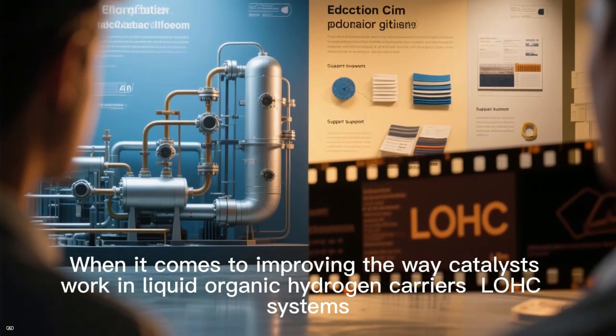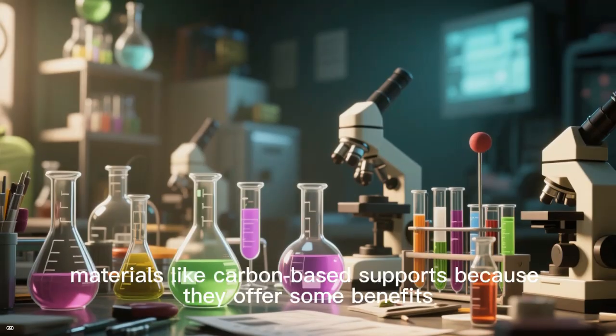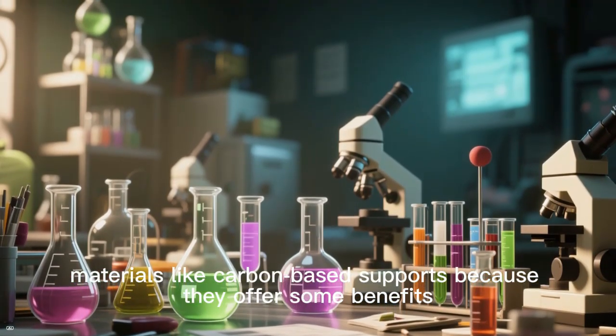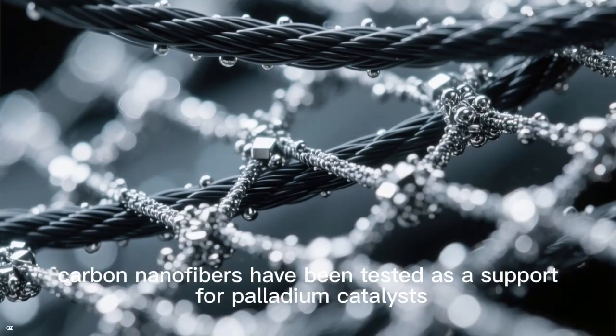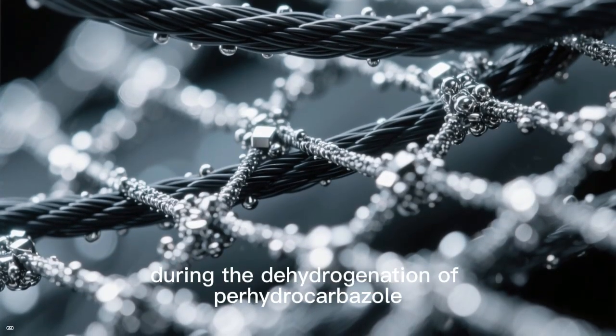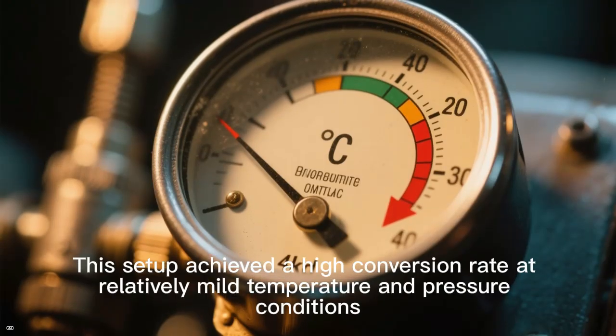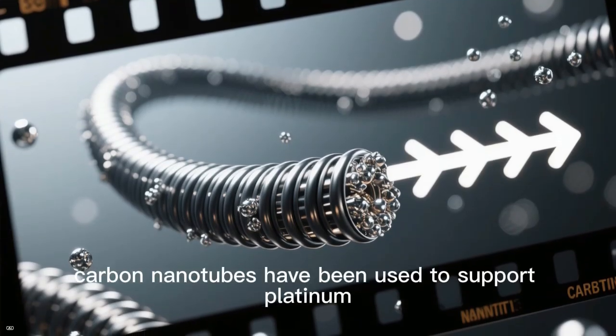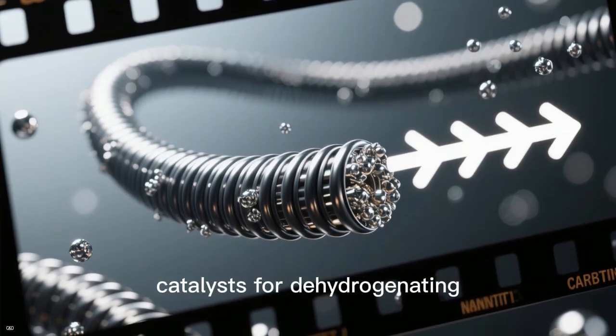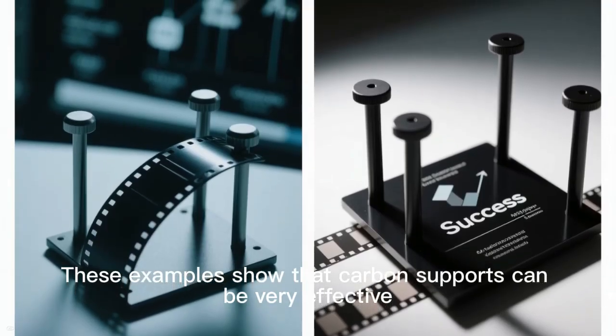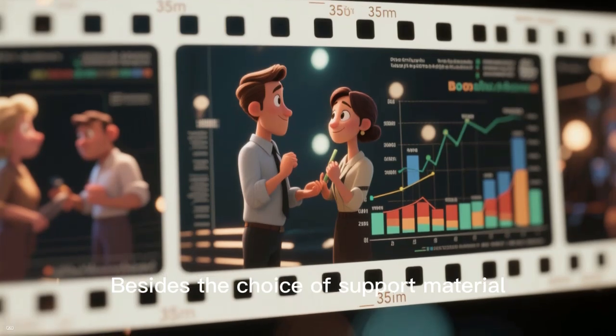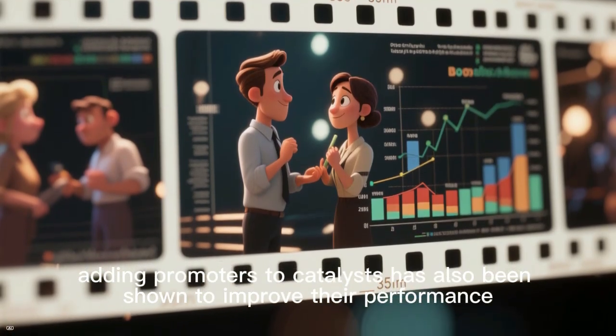When it comes to improving the way catalysts work in liquid organic hydrogen carrier (LOHC) systems, the material that supports the catalyst plays a very important role. Researchers have looked into using non-oxide materials like carbon-based supports because they offer some benefits. For example, carbon nanofibers have been tested as a support for palladium catalyst during the dehydrogenation of perhydrocarbazole. This setup achieved a high conversion rate at relatively mild temperature and pressure conditions. Similarly, carbon nanotubes have been used to support platinum catalysts for dehydrogenating perhydrodibenzyltoluene with good conversion rates even at atmospheric pressure. These examples show that carbon supports can be very effective. Besides the choice of support material, adding promoters to catalysts has also been shown to improve their performance.